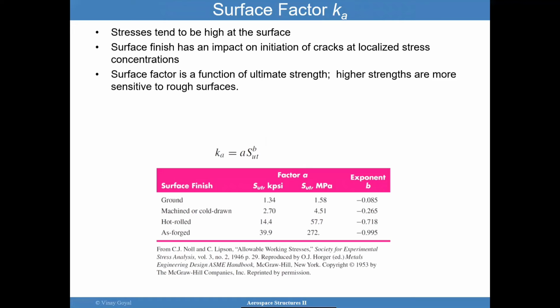So as an example, here is the surface factor case. Stresses tend to be high at the surface. The surface finish has a high impact on the initiation of cracks at localized stress concentrations. The surface factor is a function of ultimate strength. Higher strengths are more sensitive to rough surfaces, so it's important to consider that in your assessments. Here you have 4 different types: a ground one, a machined or cold drawn, a hot rolled, and an as forged condition. And then these are the various exponents and the ultimate strength provided in megapascals or ksi. These will be substituted here, and then you'll find a value of Ka. Some books will have a value of Ka depending upon what kinds of RMS surface conditions we're talking about.